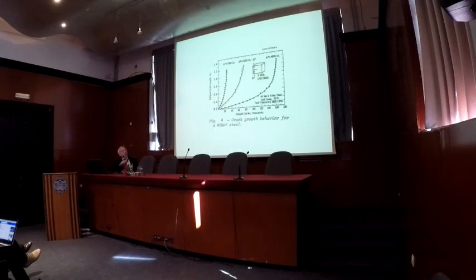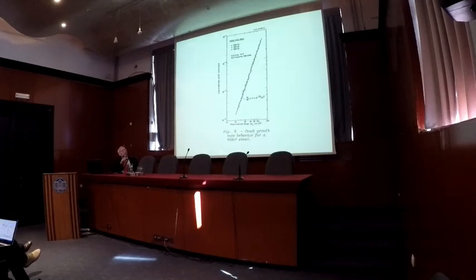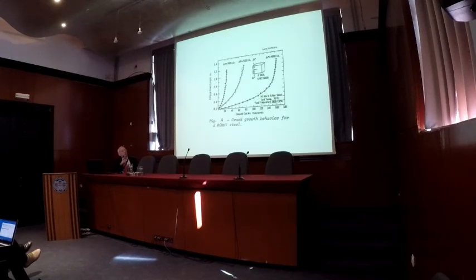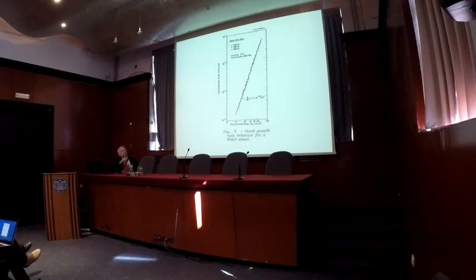Anyway, to show you that the fracture mechanics approach works, here's a set of data that were generated at Westinghouse for a constant load range, three different specimens and three different load ranges. And then the slope of this would be the da/dN, crack growth per cycle. At the point you take a slope, if you take the crack length and the load range, you can calculate a K using the formulas I showed you much earlier. Anyway, if you take these three curves and analyze them as da/dN versus delta K, they collapse onto a really nice single curve. And so for us experimentalists, to be able to collapse this onto one single curve shows you then that the approach is working pretty good.